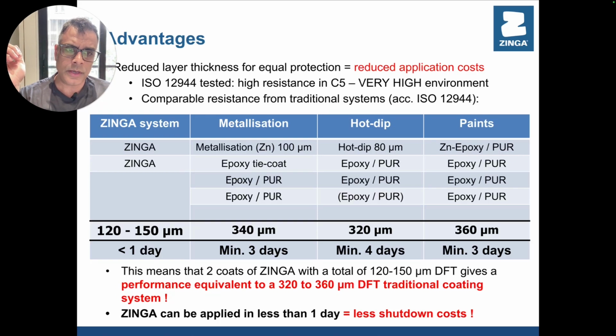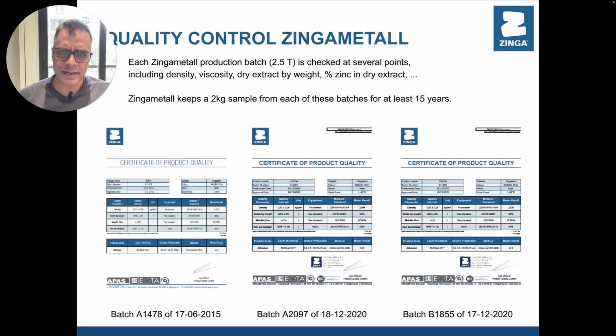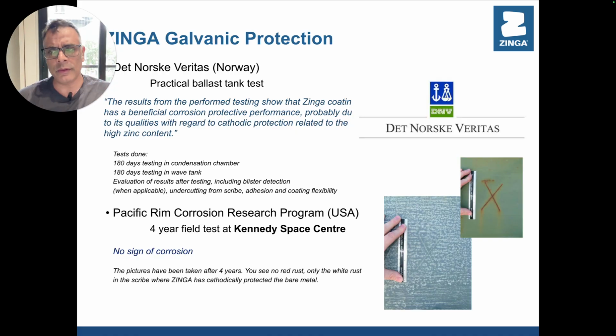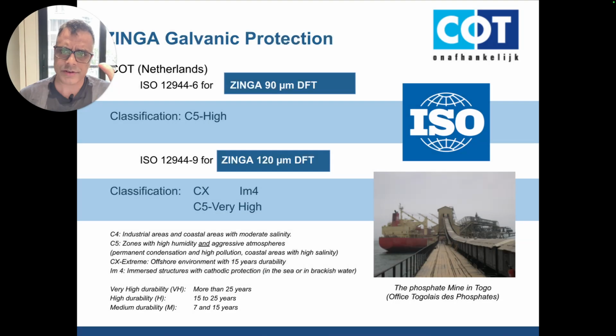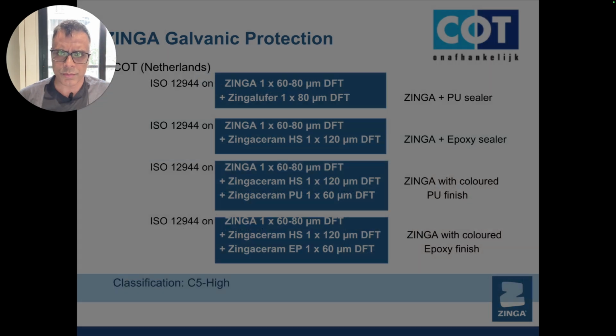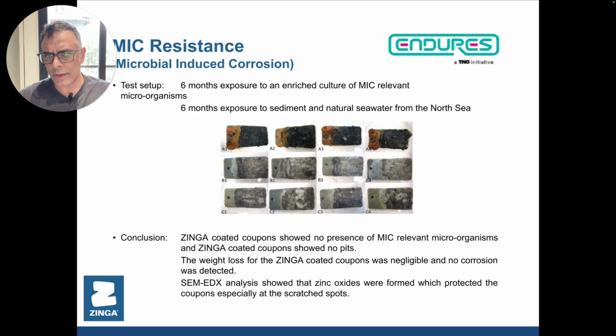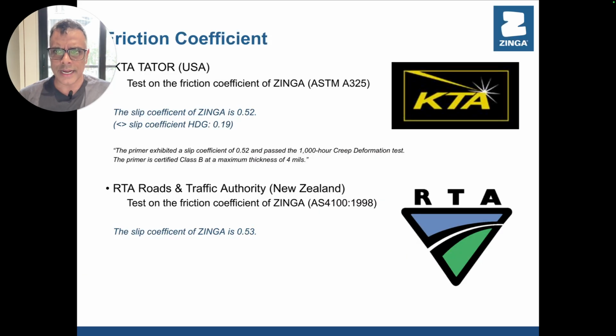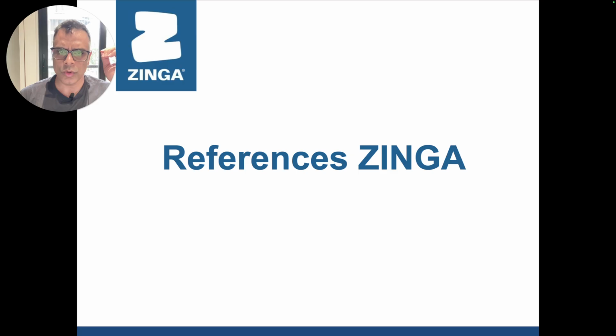Now, when you compare it to Hot-Dip, the amount of time needed for Zinga is less than a day as compared to what takes 4 days in a Hot-Dip process. So 2 coats of Zinga give the performing equivalent of 320 to 360 microns traditional coating system. A lot of advantages, lot of test reports are there. We are having a lot of European certifications, Indian certifications, etc. It is passing C5 IM also, 120 micron Zinga. So there is absolutely no problem. So I strongly recommend, we have a lot of microbial induced corrosion resistance as well, and friction coefficient is 0.52. So the abrasion is retained in the whole process.